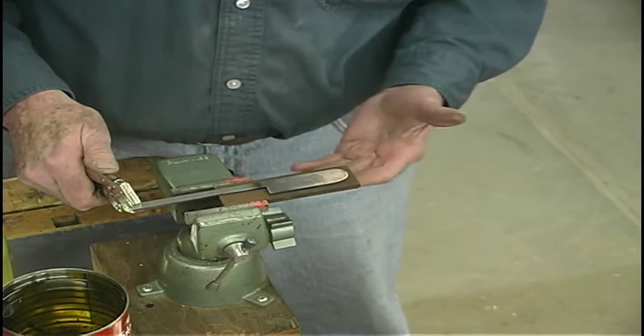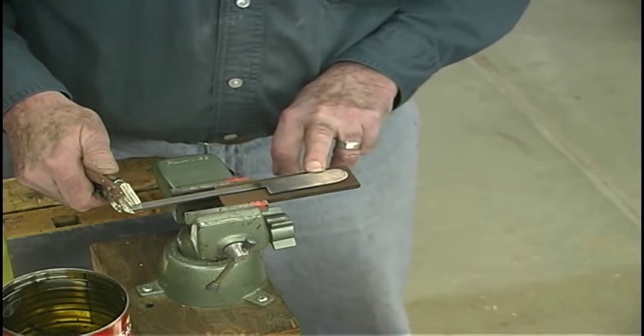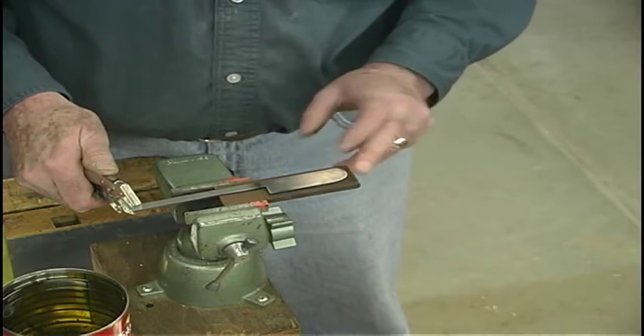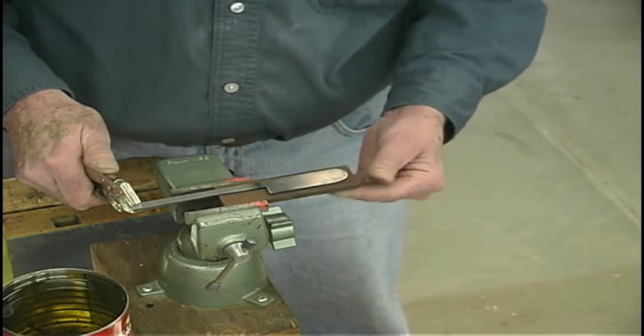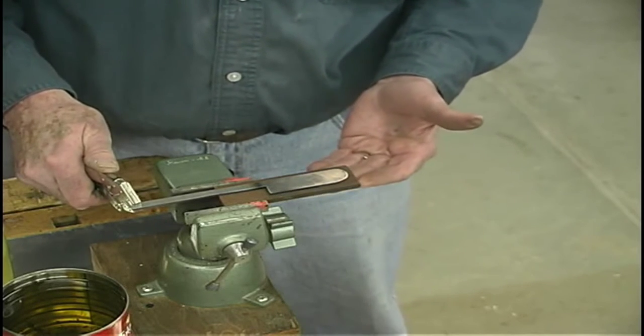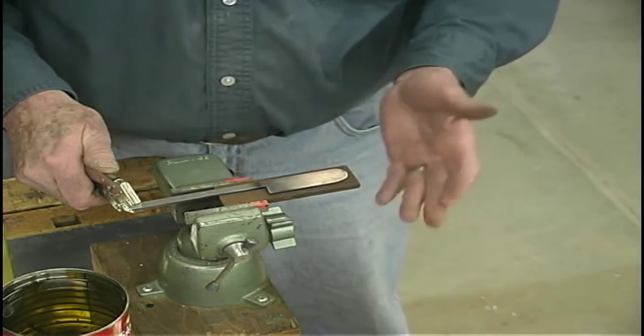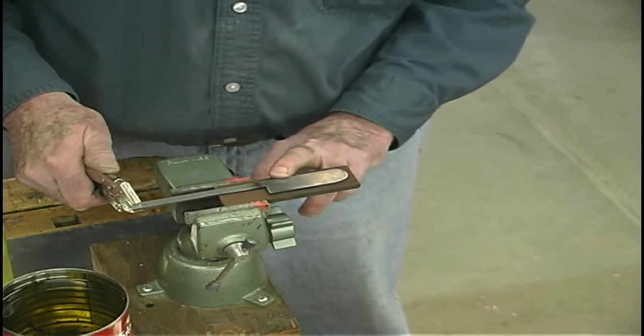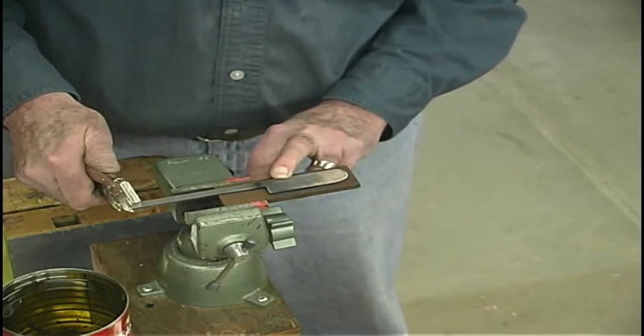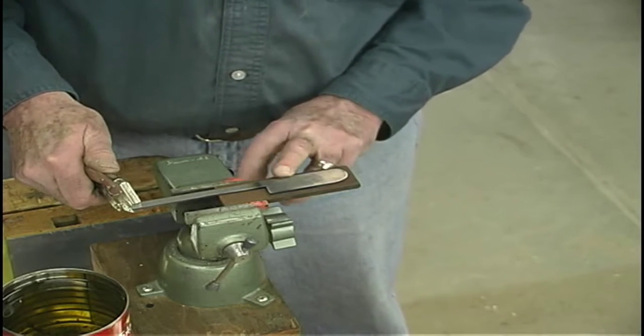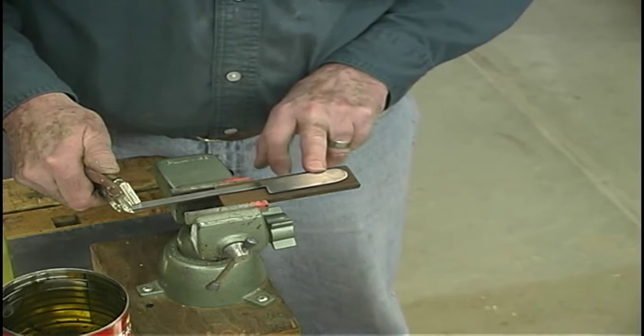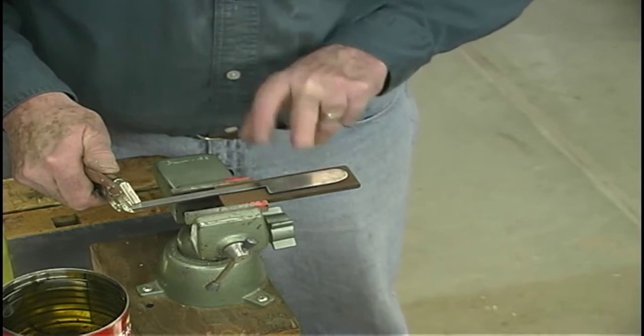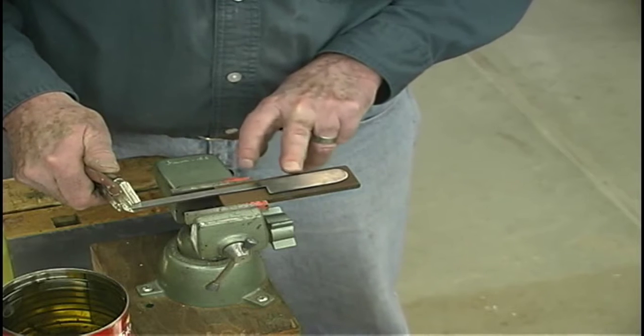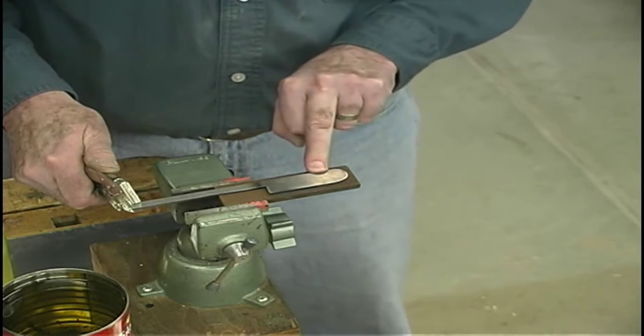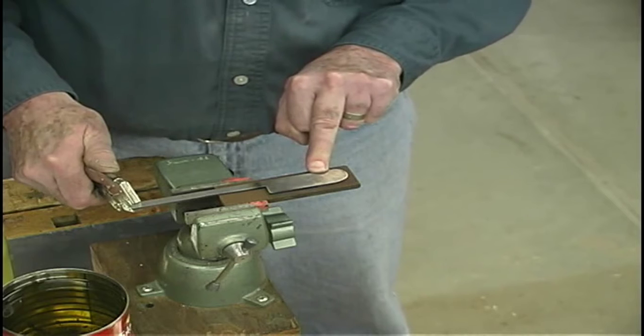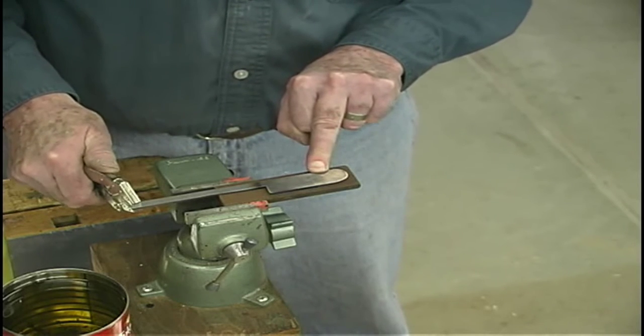Blue we're all familiar with. That's when we are grinding and we grind too hard and we notice the end gets blue. If it should get that far, we have taken all the hardness out of the steel. We would have to reheat it, quench it, and then re-temper it again. And you can only do this a few times before you burn a lot of the carbon out of the steel. So we're looking for a straw. It'll come up very slowly, but then when it starts to move, we have to quench it immediately. The darker it gets, the softer we're going to make this until we get it back to the original softness, and that, of course, we don't want to do.